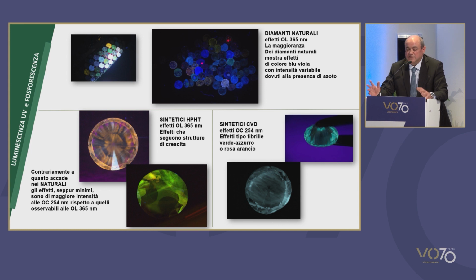Synthetic diamonds with a short wave produce a more visible, more evident effect compared to the long wave. In the vast majority of cases, natural diamonds behave in the opposite way. Stronger effect at the long wave and milder effect at the short wave.